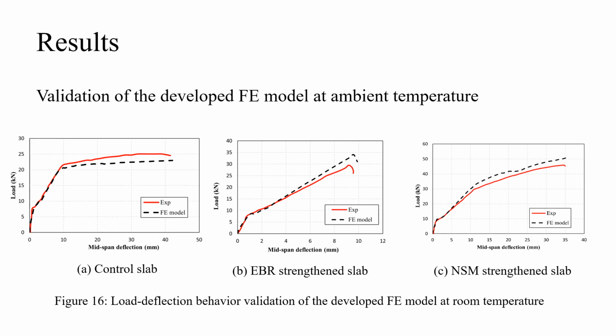Three slabs were modeled and analyzed under room temperature. The load-deflection curves and their comparison with the experimental load-deflection curves published in Acevedo et al. are shown here. It can be clearly seen that there is a good agreement between the experimental and numerically predicted curves. The finite element model can perfectly predict the behavior of the slab until yielding of steel reinforcement, indicated here by the clear change in the slope of the curve. After that, the model can predict to a good extent the slab response, with a slight under-prediction of the capacity of the control slab.